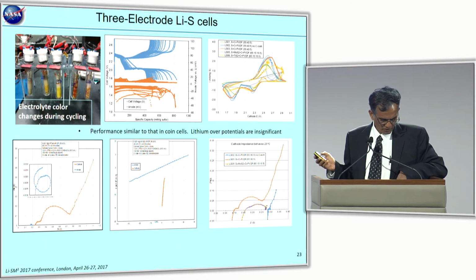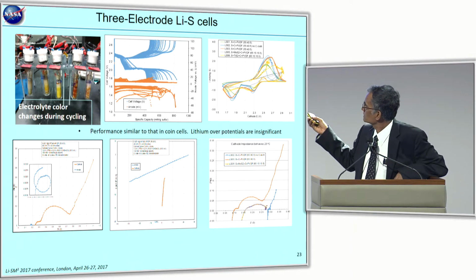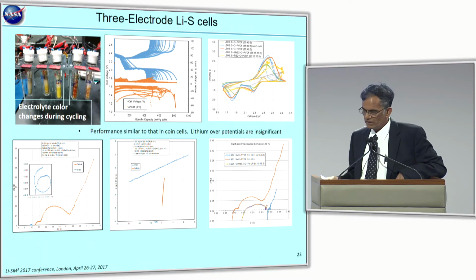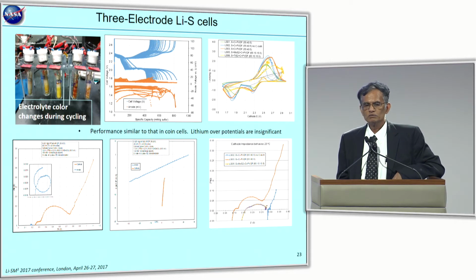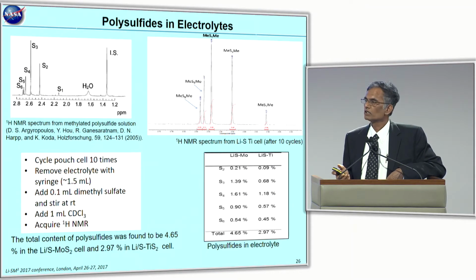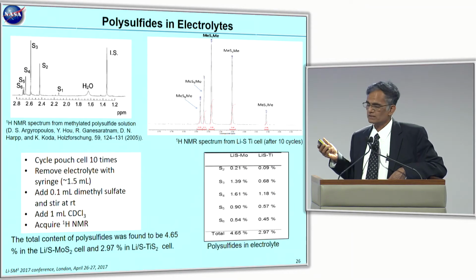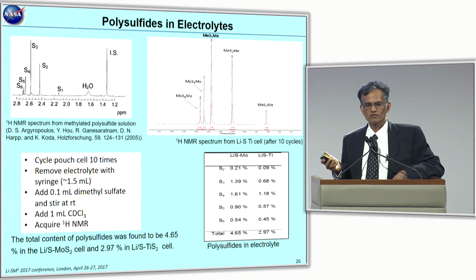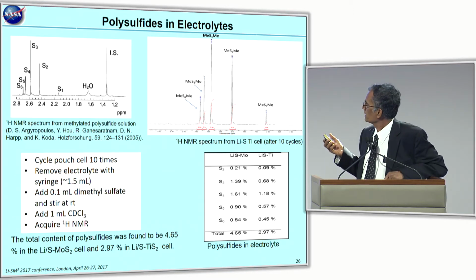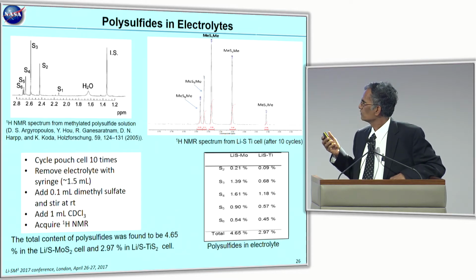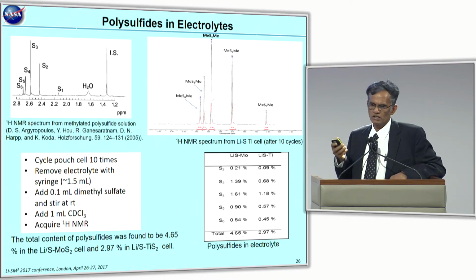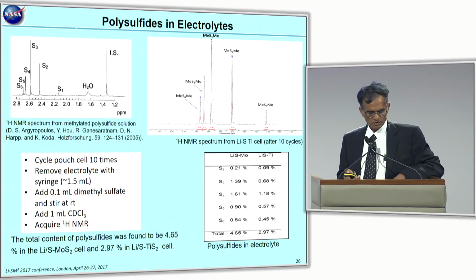And then one last thing here on the impedance side: you can see that the middle one with the carbon cloth seems to reduce the impedance. So obviously the presence of extra electrolyte seems to be helping it. We are also looking at adopting an NMR method to quantify the polysulfides in the electrolyte. And with the TiS2, we haven't really quantified it normalized to the amount of sulfur that we have, but there seem to be fewer sulfides compared to the baseline.